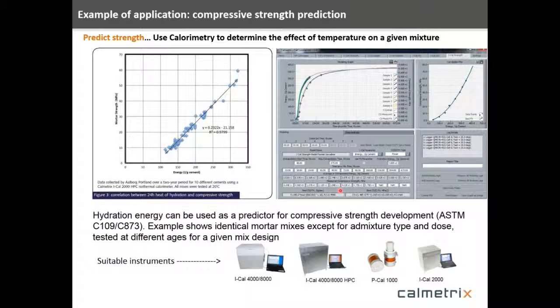And then once you've got that relationship, you can run unknown samples and basically predict what the strength will be at long periods of time. So the beauty of this technique is once you've generated a model for that mix, you can now come back and change various things within that mix in terms of admixtures and so forth. And by running a shorter term calorimetry experiment, maybe only 24 to 72 hours, be able to predict out longer term what that strength is going to be. So that's a powerful tool.